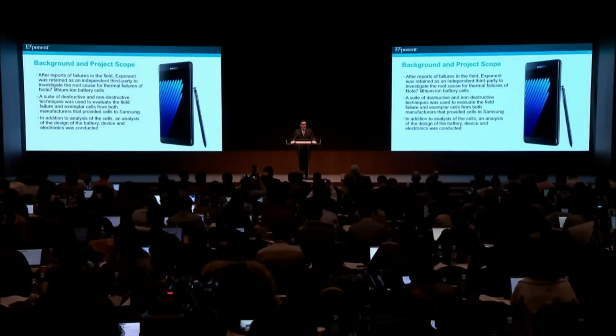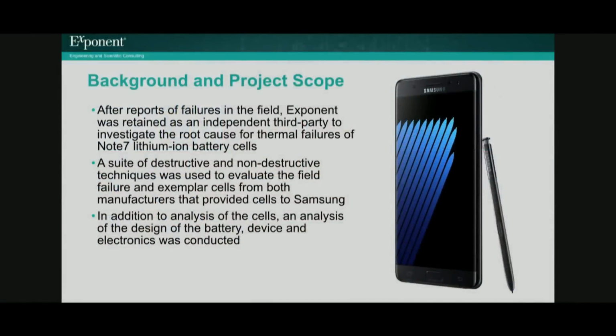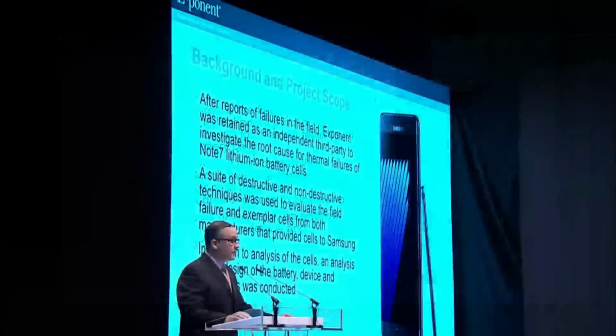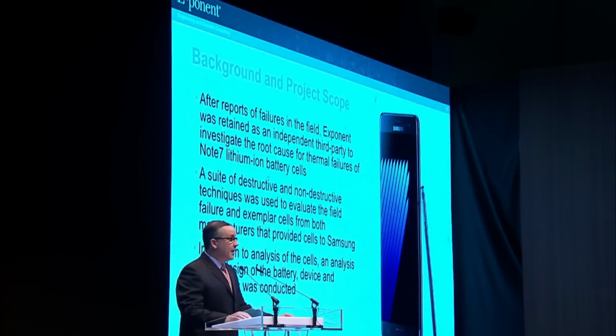Exponent was retained as an independent third party shortly after the thermal failures were reported by users in the field. The Exponent team devised and executed a suite of destructive and non-destructive tests that were applied to failed cells and devices recovered from the field, and to new unused cells and devices that were provided to Exponent by Samsung. In addition to the work that was focused on determining the issues with the lithium-ion cells, Exponent conducted an analysis of the device and accessory electronics that were related to the overall energy storage system of the Note 7.